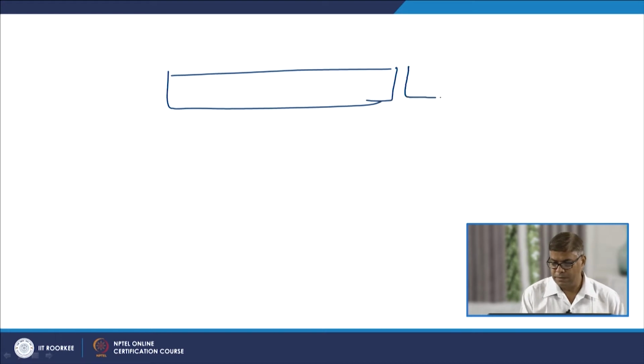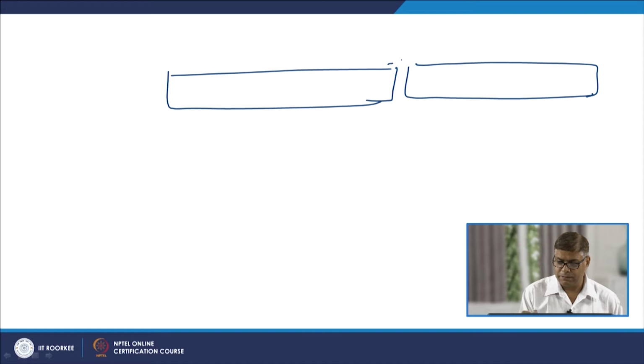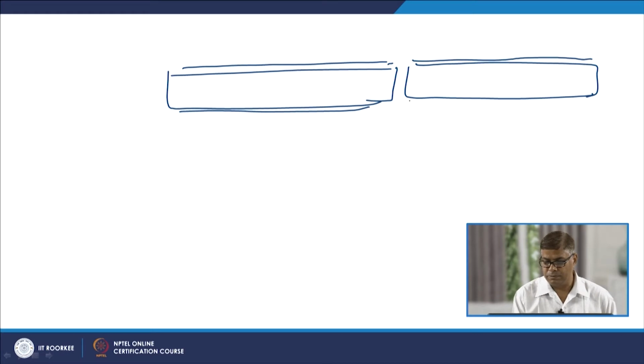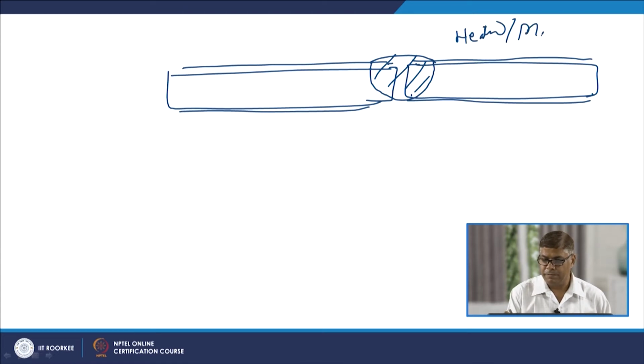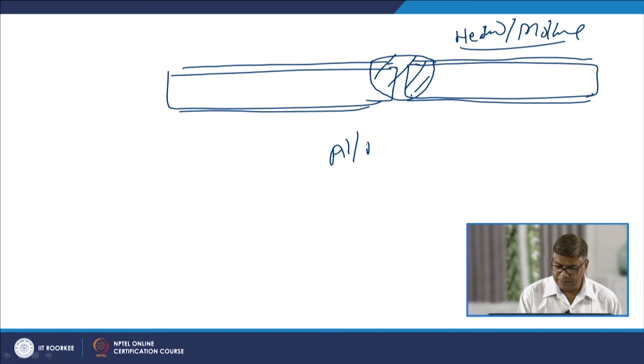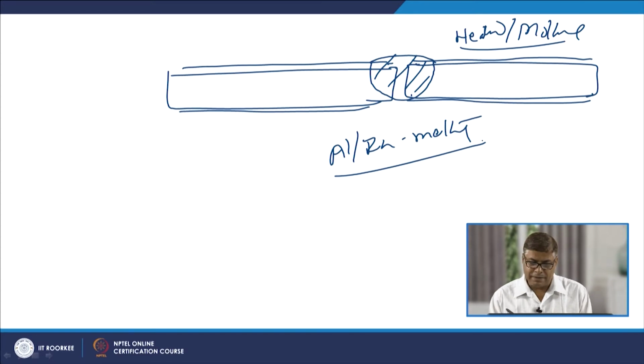like this is one component and this is another component. Say for example, these are the coated steels. So, the surface will have the coating of either aluminum or the zinc. So, for the welding purpose, when the faying surfaces of such steel sheets are fused, the zinc and aluminum will also be heated and brought to the molten state. So, basically the melting of the aluminum and the zinc, when it takes place, this interferes with the welding.